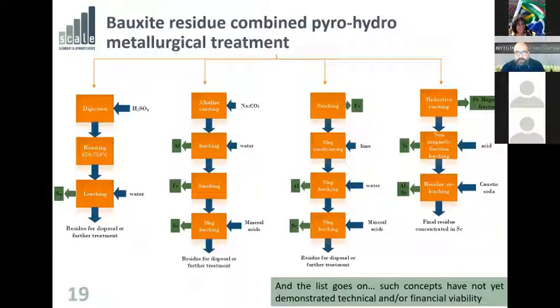The other idea is to go for a smelting that would be specially conditioned for an alkaline leaching of the slag. So if you add enough lime to your slag system, you can form phases that are leachable in alkaline environments. So you can recover the aluminium from the slag, and then from the eventual residue, recover scandium. This is a variation of the Pedersen process, which also was tested as an alternative to the Bayer process many years ago. And finally, you can do reductive roasting.